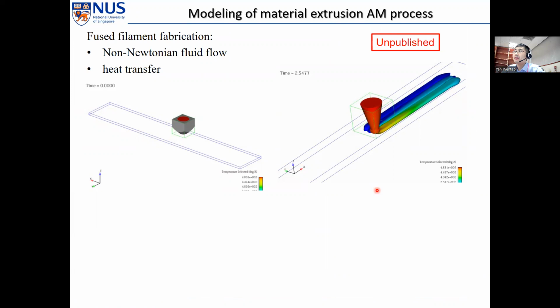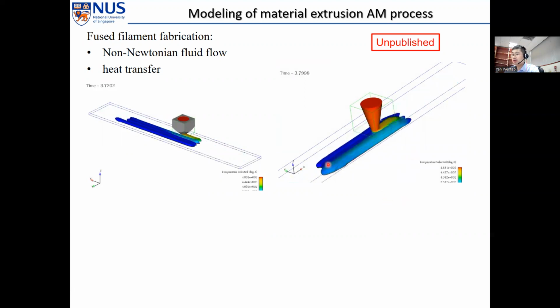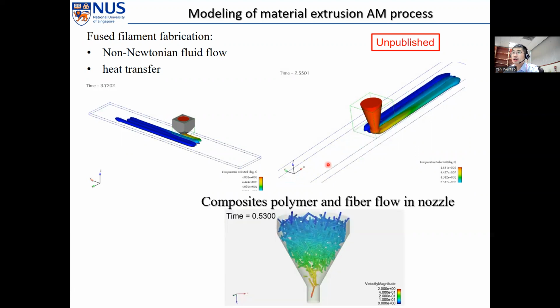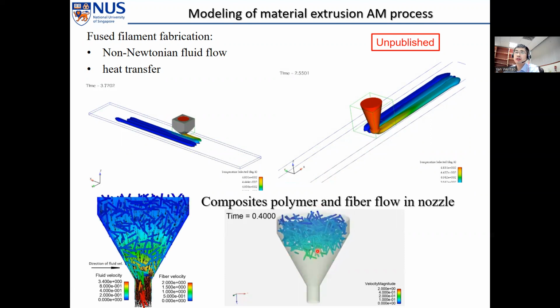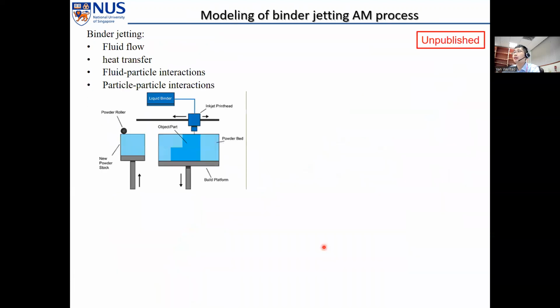Other additive manufacturing processes, like the material extrusion AM process or fused filament fabrication, where non-Newtonian fluid flow and heat transfer are incorporated, we can simulate in our model. Even when it's not just a polymer flow and there are reinforcing short fibers inside, we can also simulate their interactions and the heat exchange between them, so that we can predict the orientation and distribution of the short fibers in the as-built part.